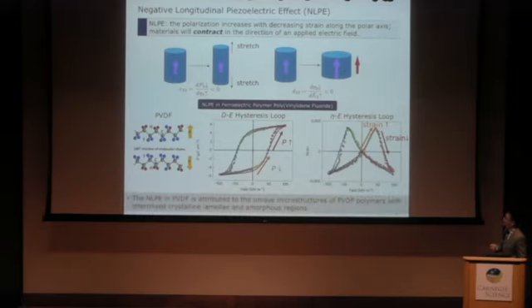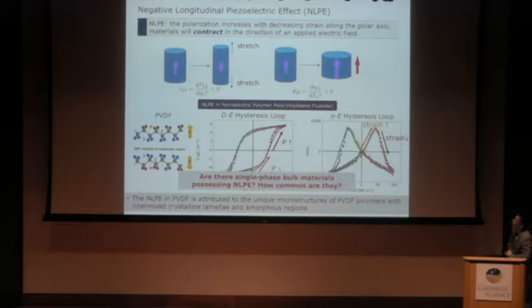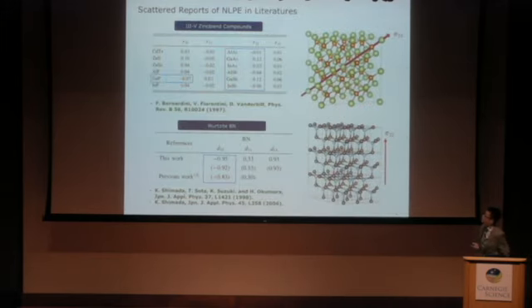In the paper, they attribute this negative piezoelectric response to the unique microstructure of PVDF polymers, with intermixed crystalline phase and amorphous phase. So in other words, it's not an intrinsic bulk property. So the question I would like to answer is, are there single-phase bulk materials possessing this negative response, and how common are they? I looked into the literature.